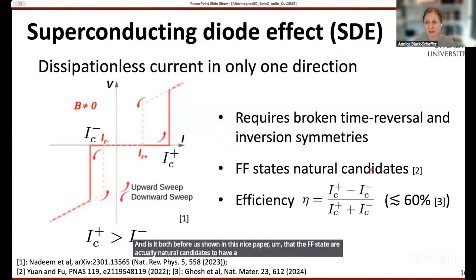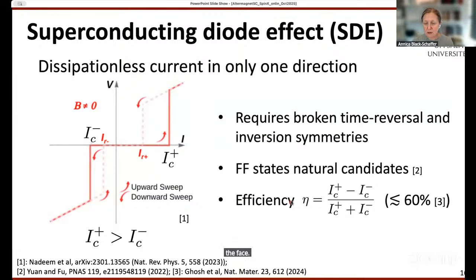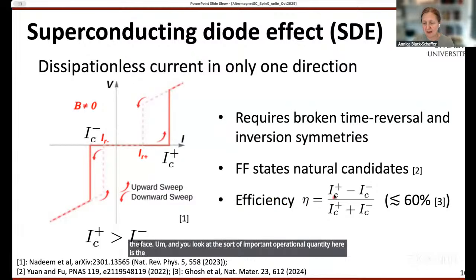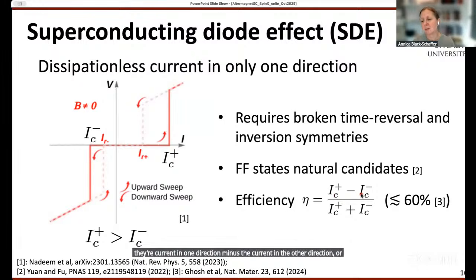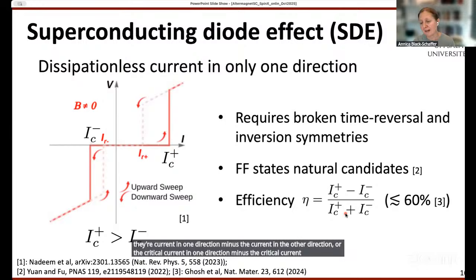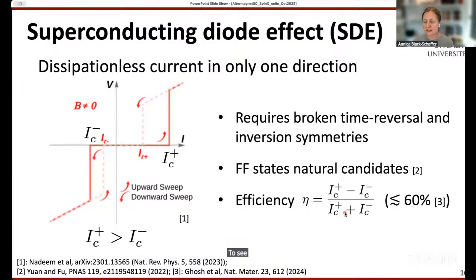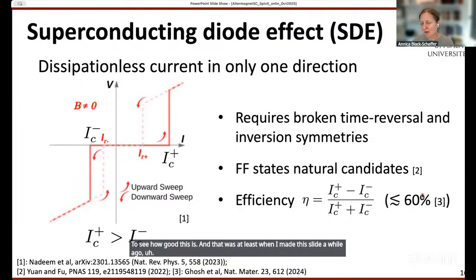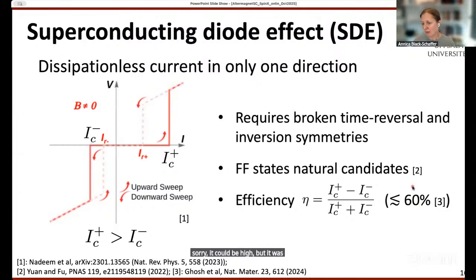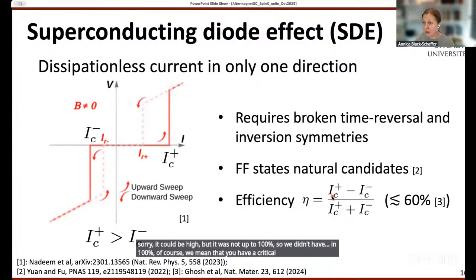So we knew that already when we set out, because they do break time reversal symmetry and inversion symmetry, because they modulate their phase. The important operational quantity here is the efficiency, where you take the critical current in one direction minus the critical current in the other direction, divided by the average, to see how good this is. At least when I made this slide a while ago, it could often be high, but it was not up to 100%. By 100%, of course, we mean that you have a critical current in one direction and nothing in the other direction.